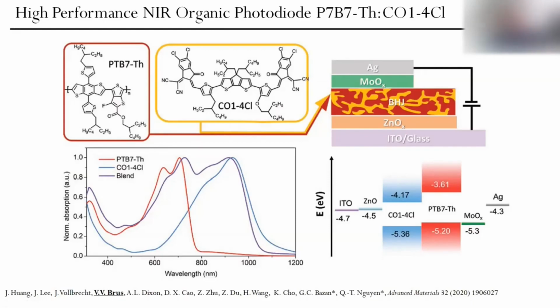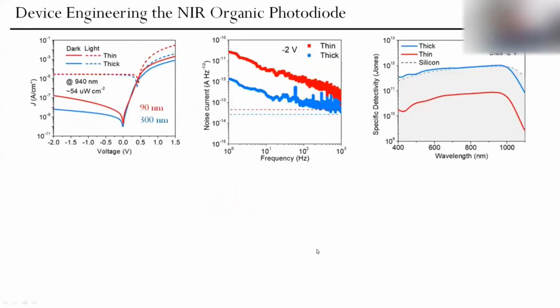And that is a very interesting application of organic semiconductors because until recently, we were working only with Fullerene based acceptors, and those possessed larger band gaps. So we couldn't reach high absorption in the long wavelength region, and organic near IR photodiodes just couldn't exist because we didn't have an appropriate material for this application. But nowadays it's going further, and these ultra narrow band gap organic semiconductors allowed us to reach high performance, high light absorption in the long wavelength region.